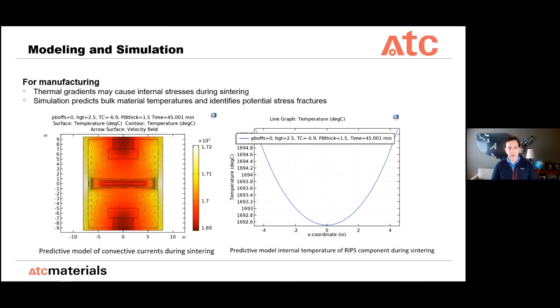And that allows you, if you know the constituent material properties, so the coefficient of thermal expansion, for example, to identify the internal stresses on a part before you make it and develop a sintering schedule that will keep those stresses under threshold to prevent cracks or fractures during the sintering process. So that's just an example of how we can use some computational tools to help not only develop materials, but to develop processes to help us manufacture those materials better.